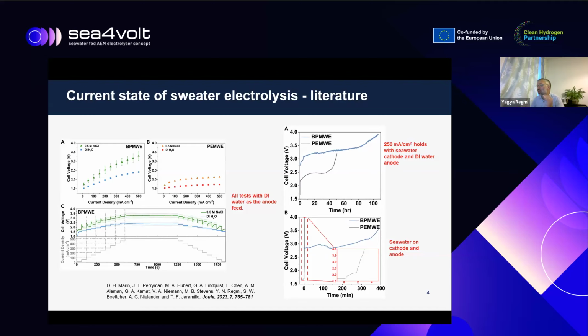I know there is a lot of stuff on the screen, but the take home message here is that when you use bipolar membrane water electrolyzer, the potential for water electrolysis definitely increases because you are using two membranes, you are increasing cell resistance, and so on. But our hope, which we demonstrate here, if you look on the two graphs on the right-hand side, is that the bipolar membrane electrolyzer, although the potential is higher, is stable for a much longer time when you start feeding seawater instead of purified water. Next slide, please.